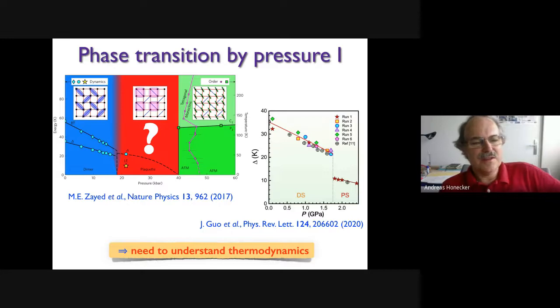The upper left is an attempt to drive it from the exact dimer state to the Néel state by applying pressure. These also saw a plaquette phase in between that unfortunately didn't correspond to expectations. There's another work that came out two years ago that measured the spin gap here as a function of pressure. And both of these works, I think, claim to have seen a phase transition. But once again, in a pressure cell, you can't do that much. So again, this is mostly thermodynamic measurement, and that means another argument to understand the thermodynamics.